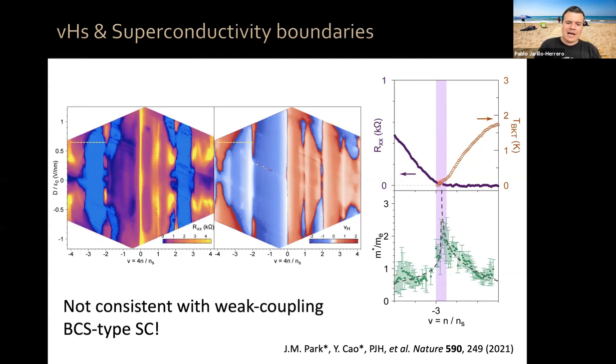Yeah? Now, this is very much unlike weak coupling BCS type superconductivity, where your critical temperature increases exponentially with increasing density of states, okay? So in a regular BCS type superconductor, you expect that an increase in the density of states would lead to an exponential increase in TC. Here, not only it doesn't increase, it actually decreases, and at the maximum, when we would expect the TC to be the maximum, it actually is zero, and from there on, is zero, okay? So this is something which is quite peculiar.